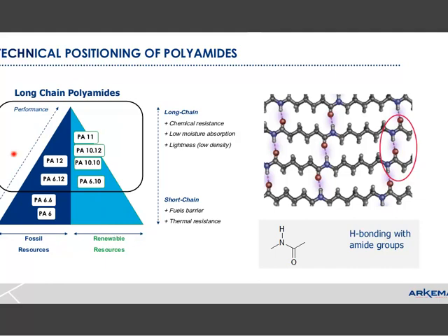And then we show a performance pyramid where at the top we have the best performing products. For these materials at the top, which tend to be our long-chain polyamides, they provide chemical resistance, low moisture absorption, lightness, and what I'll explain is good low temperature impact, good impact properties. The short-chain products, due to the higher amount of amide linkages, will have higher crystallinity and provide better fuel resistance and thermal resistance.